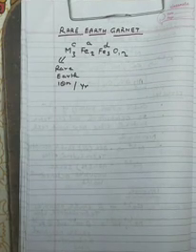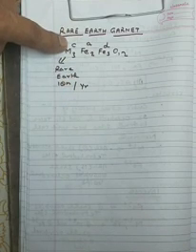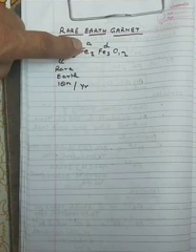Clear? So the rare earth ion or yttrium in the structure fills the dodecahedral voids. There are a total of 5 Fe atoms. Out of 5, 2 Fe will sit at the octahedral voids, and 3 will sit at the tetrahedral voids.